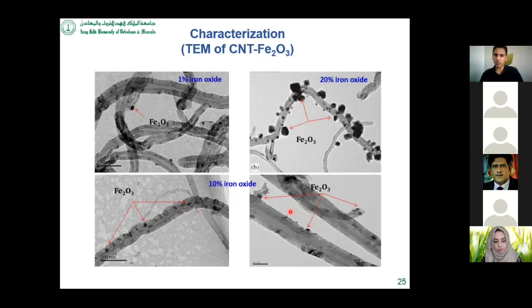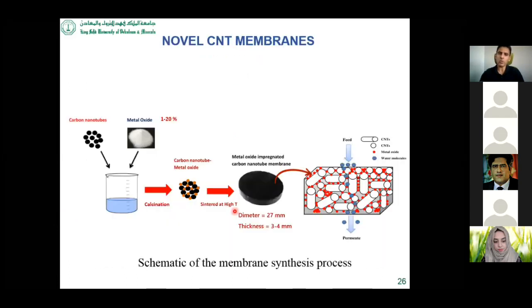At 10%, we are getting somehow the optimum dosage. So the particle are attached to the surface uniformly. So what we did basically, first we modify the surface of the carbon nanotube. There is an easy procedure, calcination and some sonication is involved. And then we basically compact this metal oxide modified carbon nanotube using a specific die. And then we sinter at high temperature.